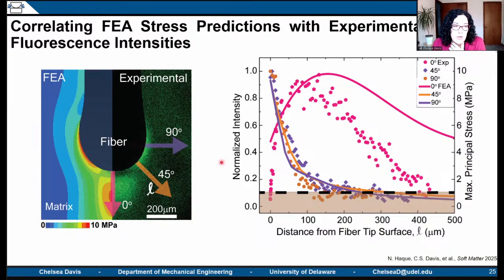However, for his 0 degree, or right here in the direction of the pulling, or directly opposite to the pulling, we observed a much more diffuse or larger deformation zone than the much more narrow, concentrated stress concentration that was calculated by the finite element analysis. And you can see that reflected here, where this solid line is the FEA, and it's way higher and tails off in a different way than this more diffuse observation that we had.